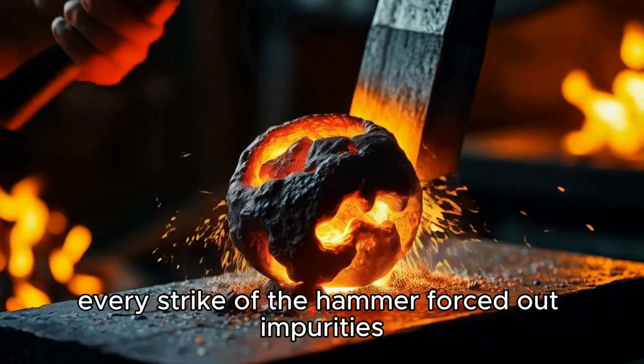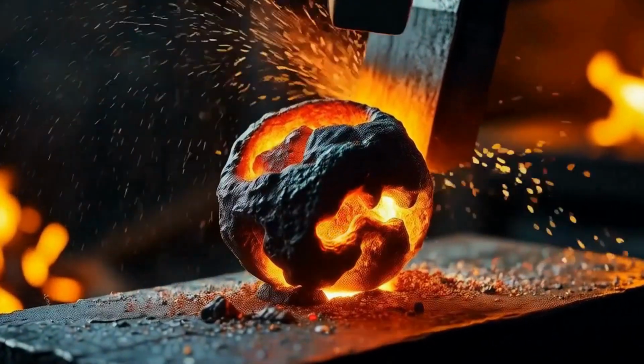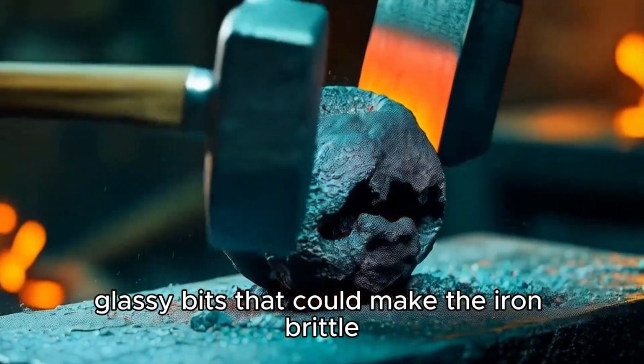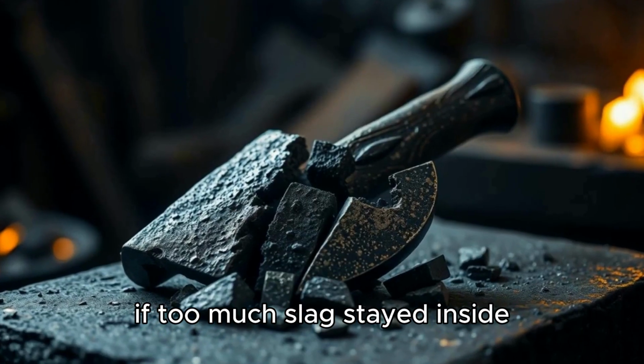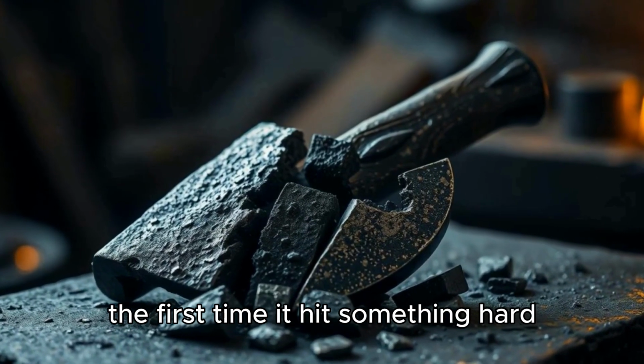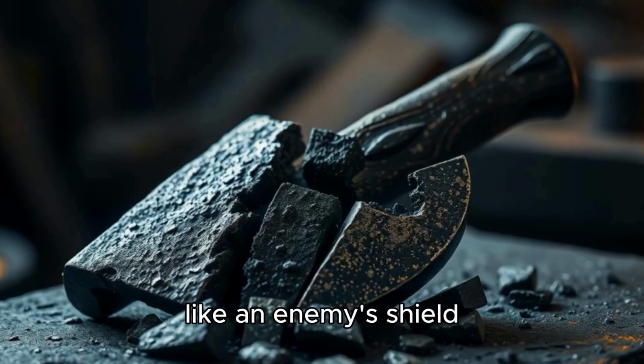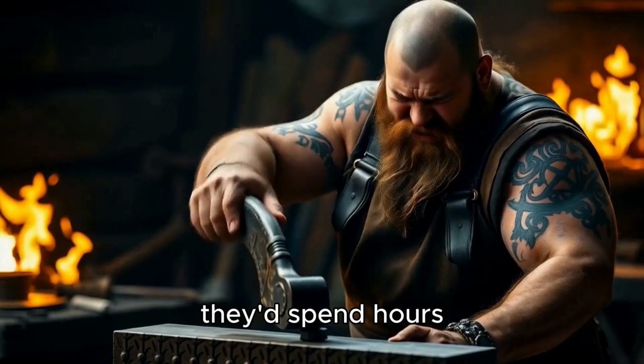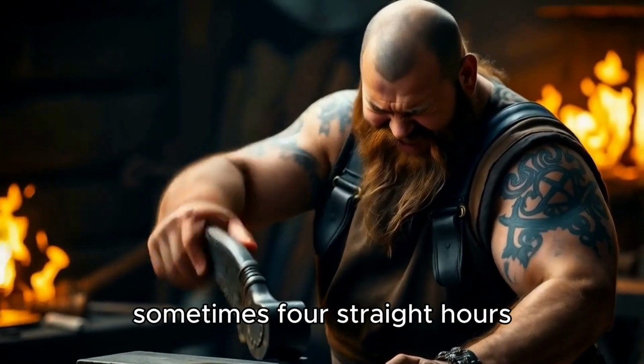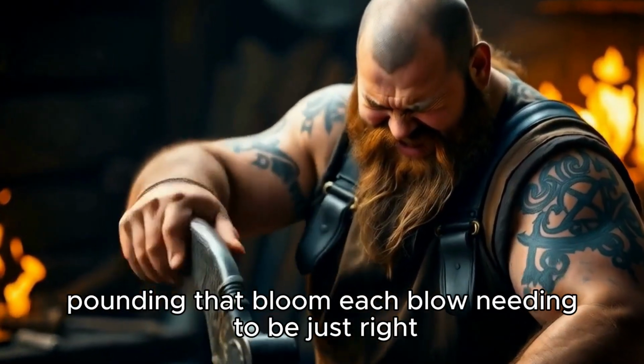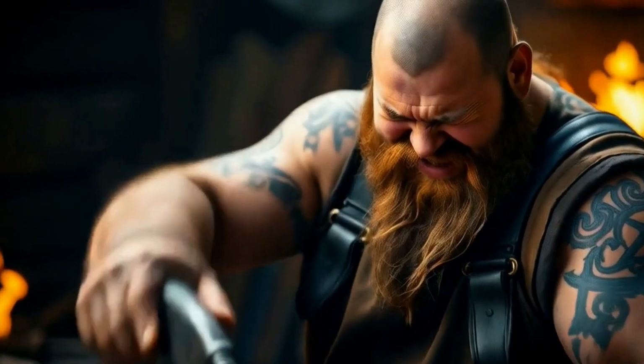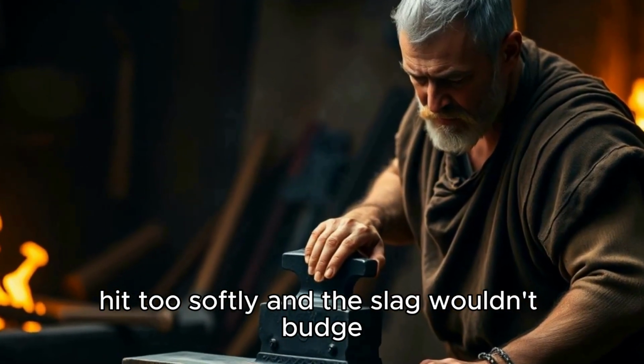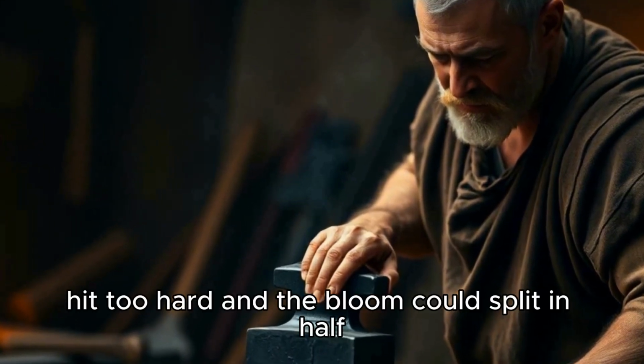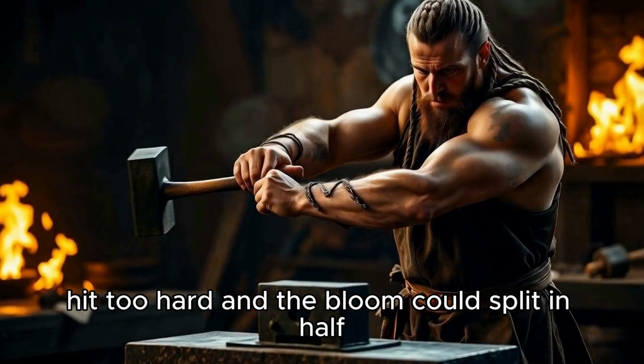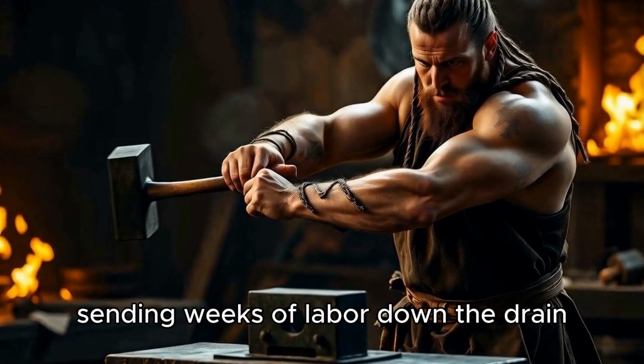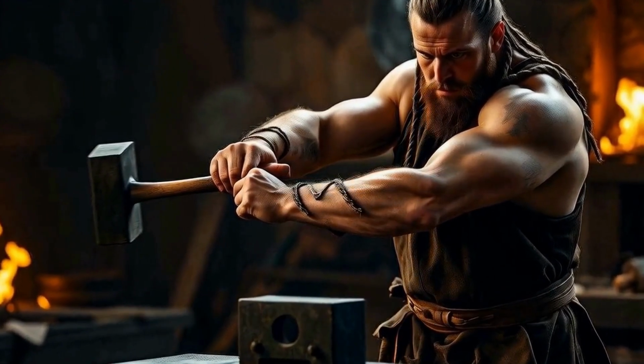Every strike of the hammer forced out impurities called slag, glassy bits that could make the iron brittle. If too much slag stayed inside, the axe would shatter the first time it hit something hard, like an enemy's shield. They'd spend hours, sometimes 4 straight hours, pounding that bloom, each blow needing to be just right. Hit too softly, and the slag wouldn't budge. Hit too hard, and the bloom could split in half, sending weeks of labor down the drain.